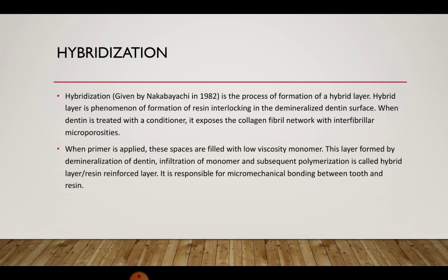When the dentine is treated with a conditioner, it exposes the collagen fibril network with interfibrillar microporosities. So when we apply a mild acid, the smear layer is removed and the collagen fibers are exposed. So the collagen fibril network is exposed, and this network has interfibrillar microporosities. When the primer is applied on this exposed collagen mesh, these interfibrillar microporosities or spaces are filled with low viscosity